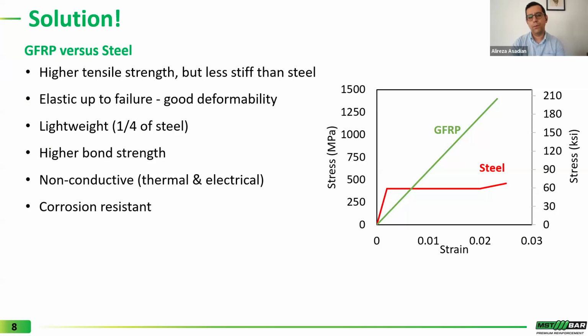Now, what are the mechanical properties of GFRP bars versus conventional black steel rebar? GFRP bars have very high tensile strengths, but they have lower modulus of elasticity. The material is elastic up to failure, as you can see in the graph on the right side of this slide. However, reinforced concrete elements made with GFRP bars will have very good deformability, and deformability is essentially the ability of a member to take very considerable deformation or deflections before failure.